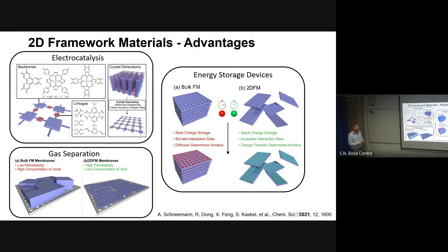So I've been talking now a lot about these framework materials. Why do you actually want your material to be so thin? What are the advantages? So in electrocatalysis, for example, if you have a functional unit in your material that contains an active metal site, the downsizing can, for example, affect the band gap of the overall framework, and you have better access to the catalytic sites. So the catalytic sites are on the freestanding framework and not buried somewhere in the middle of your material. You should have a much higher turnover.